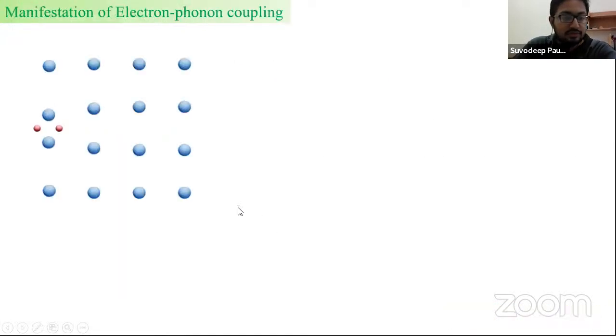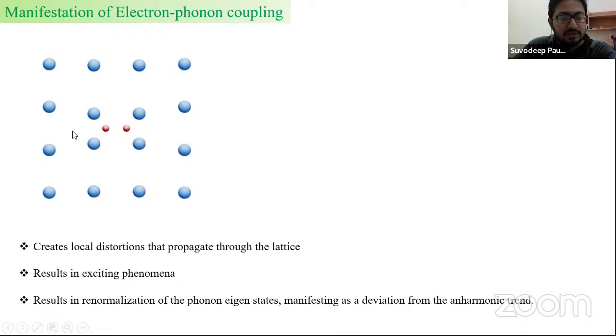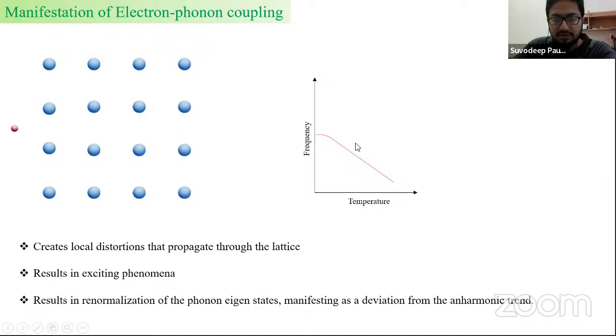So further, if we allow the interaction of the lattice with electronic charges, this GIF shows some sort of interaction of that sort. What happens is we see a local distortion that propagates through the crystal, and this sort of interaction gives rise to a lot of exciting phenomena, including superconductivity. And as can be quite easily imagined, this would also change the phonon eigenstates, and therefore these interactions might be manifested as a deviation from the anharmonic trends that we just discussed.